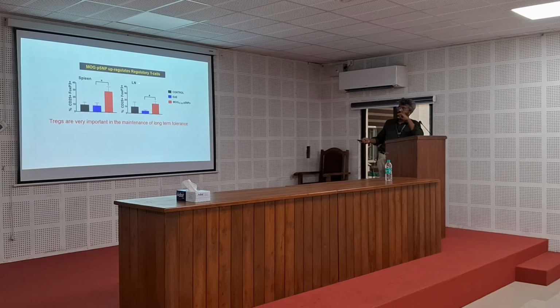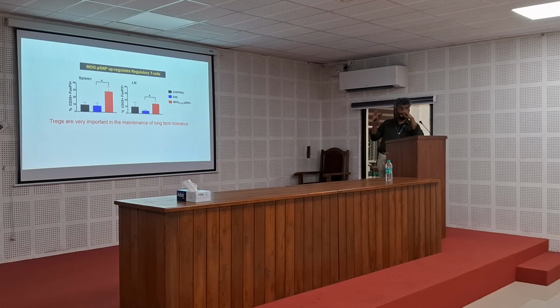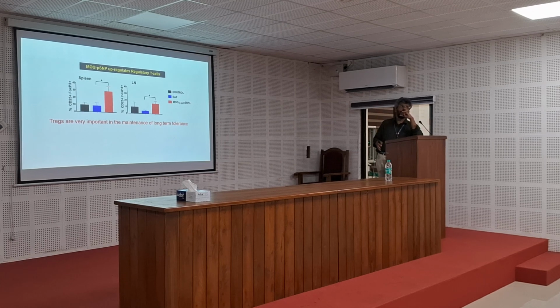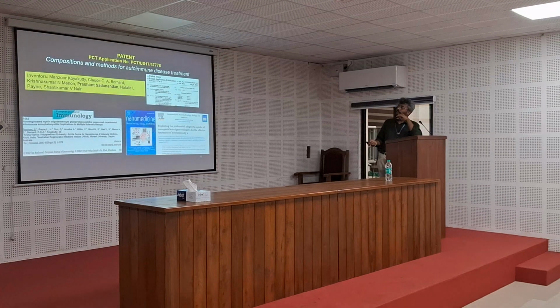We wanted to check these regulatory T cells. We took out the spleen and lymph node from the treated group, and tried to see how the regulatory T cell content is. You can see the red line, the treated one, where the regulatory T cells were upregulated, and that was probably the reason we didn't see any relapse up to 60 days. So regulatory T cells play a huge role in maintaining tolerance for a long term. This work was filed for a patent and published in 2 journals.